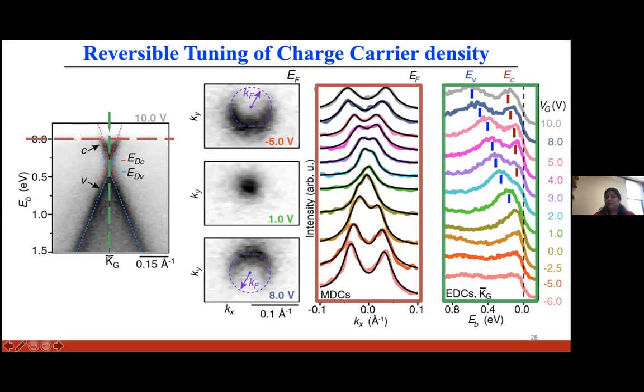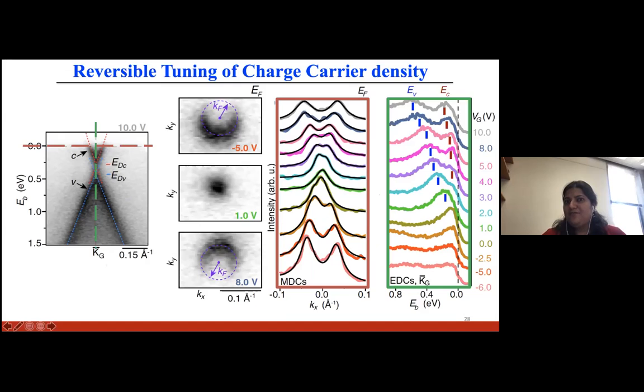So here EV is the peak, essentially the V branch crossing. And you can see that this peak remains fully below the Fermi level in our spectra for all gate voltages greater than or equal to 1 volt. And this C branch crossing, which is this peak here denoted by EC, you can see it is separated in binding energy from this peak. And it remains below the Fermi energy for all gate voltages greater than or equal to 3 volts.